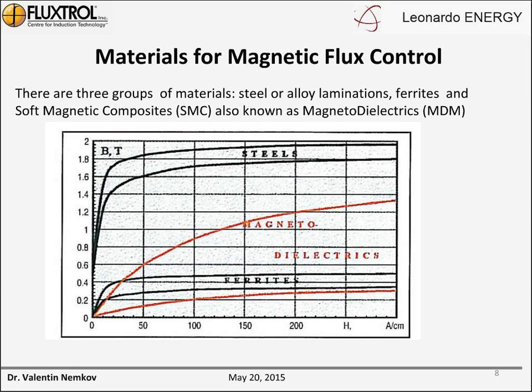The BH curves of these groups of materials are on the picture. For steels, it's very well known. The magnetic flux density grows very quickly with magnetization force, and then it reaches saturation or an area close to saturation, which for laminations is approximately 1.8. If we keep in mind the space between the sheets, it will be maybe 1.7 Tesla, the equivalent saturation flux density of steel laminations.